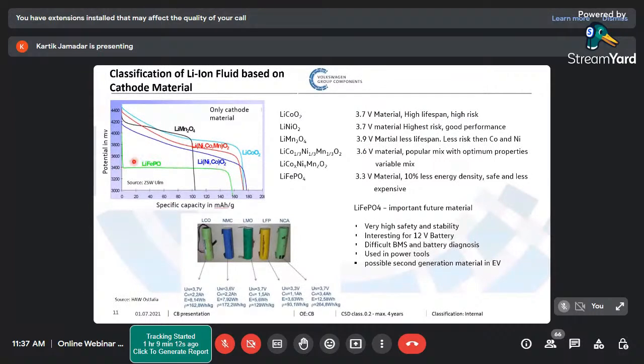It means it starts around 3.3, 3.4 volt, and immediately till the end, it is always having the same flat curve. And by somewhere before the capacity is fully gone, it goes down. That makes it difficult to analyze exactly how much capacity has been used by this cell, because at every capacity the voltage will remain the same.